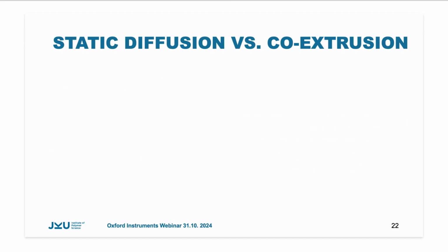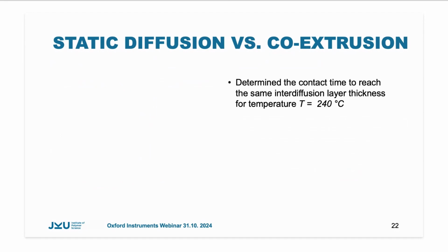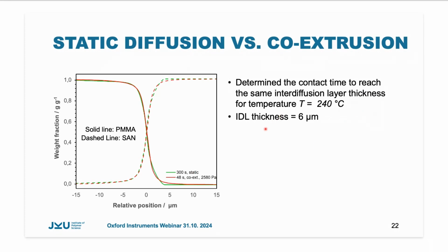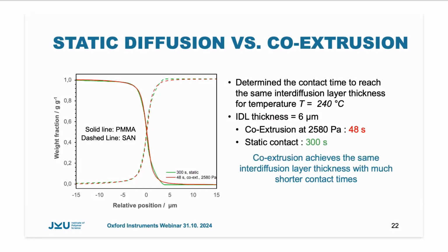To compare the results of static diffusion and co-extrusion experiments, we determined contact times to reach the same interdiffusion layer thickness for a given temperature. We choose a thickness of 6 micron, and this is reached after 48 seconds in contact for our co-extrusion experiment and after 300 seconds for our static experiment. This shows that with co-extrusion, you achieve the same interdiffusion layer thickness with much shorter contact time and proves that shear stress improved diffusion properties of the polymeric materials.